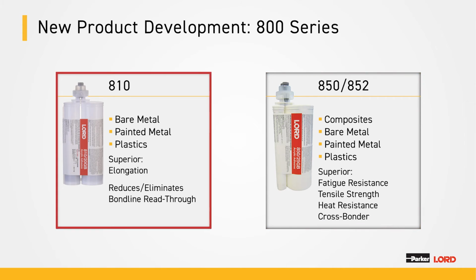The 810 was developed to eliminate read-through, which if you're not familiar with it, read-through is a phenomenon where you can see the footprint of the adhesive show through the backside of ACM or even a thin gauge metal panel like aluminum. It is highly flexible with 190% elongation, and it does great in applications with a wide CTE mismatch